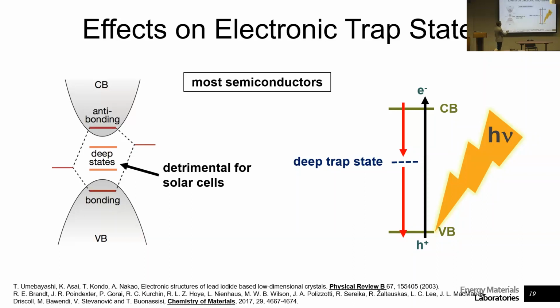That electron sits there. Let's say it's 300 millielectron volts. That's really a lot of energy, an order of magnitude higher than thermal energy. So that electron will not go up into the conduction band through thermal energy. Instead, it will sit there for a while and then finally go back down and recombine with the hole that it left in the first place. So this becomes a dead end, right? That electron doesn't get out of the cell, and we don't get current.